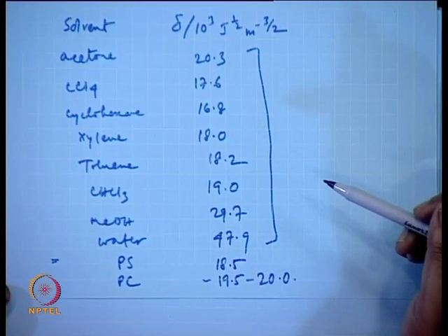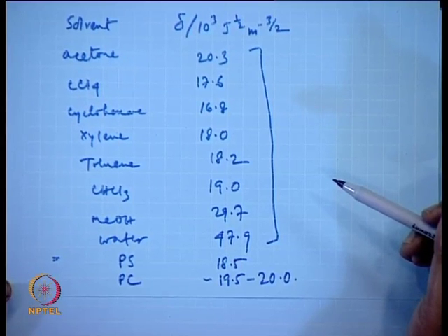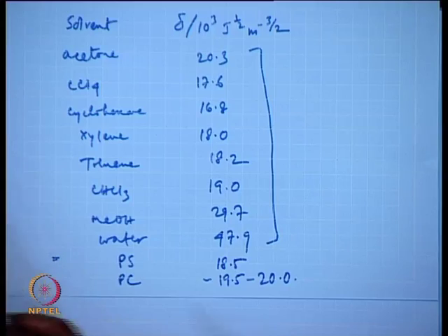For example, if you want to use medical devices like syringes and other medical components, in most cases before use they are sterilized by applying rectified spirit, which contains alcohol. Now, if you know the solubility parameter of that alcohol, you can narrow down the choices of polymer which will not be soluble in that alcohol used for wiping or sterilizing the equipment. So, you can reduce your number of experiments or your choice of polymers by prior knowledge of the solubility parameters of the solvent and polymer.